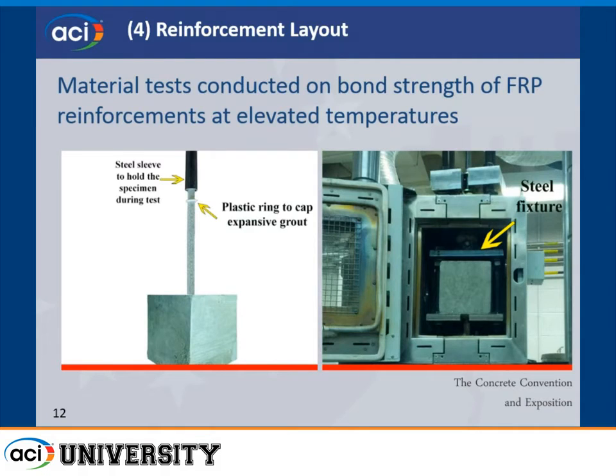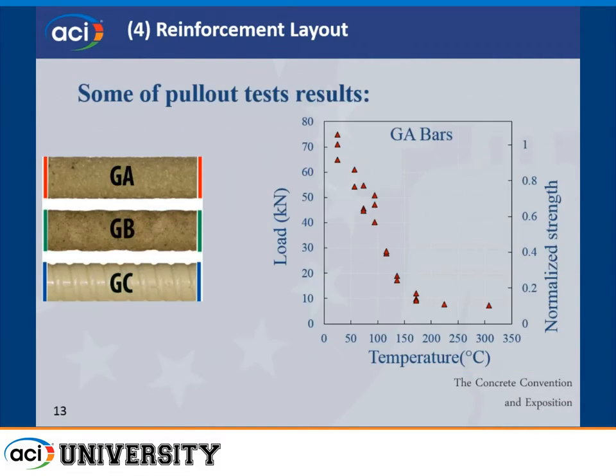So this shows our high temperature furnace. We did some pull-out specimens to see, and you can see quite quickly we get a drop-off of bond strength. Certainly at 100 degrees Celsius, 212 Fahrenheit, we've lost a considerable amount of bond strength.